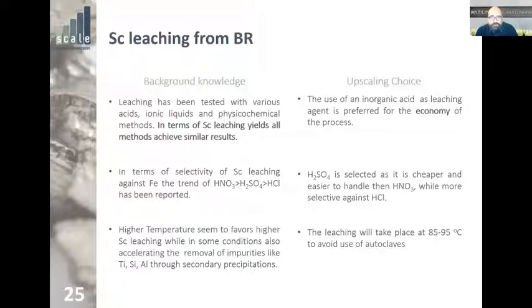So we had all this knowledge about how many things we could use in terms of leaching, and we have to make a choice as to what we're going to use in our pilot. So first of all, we said for economical reasons, we will select an inorganic acid, as anything else seems to be driving the process very, very far away from any economical meaning. Then we know from the mineral acids that in terms of selectivity against iron, the trend is nitric, sulfuric, and hydrochloric. Here we will choose sulfuric because it's cheaper and easier to handle than nitric, but still more selective than hydrochloric acid. Finally, we will opt to use higher temperatures, which seem to favor scandium leaching in some conditions, and also in dilute solutions seem to accelerate removal of impurities like titanium, silicon, and aluminium.